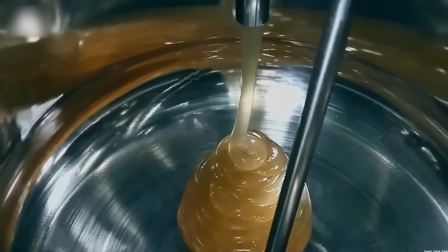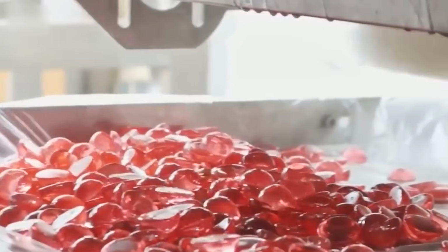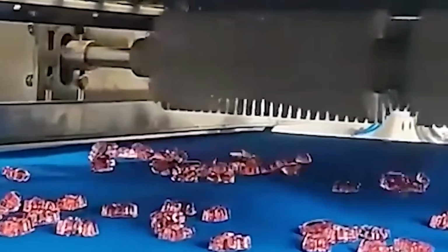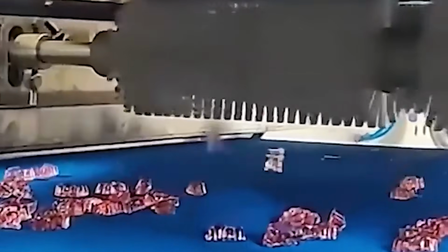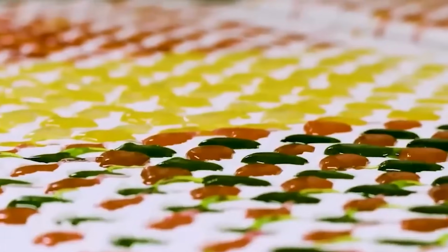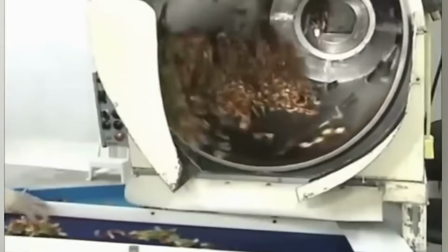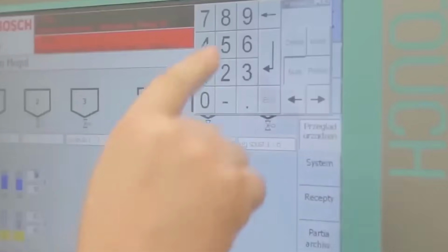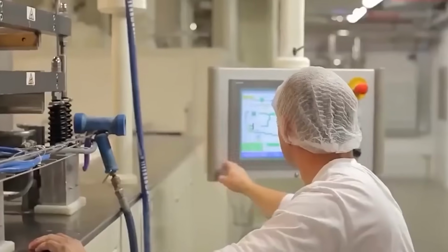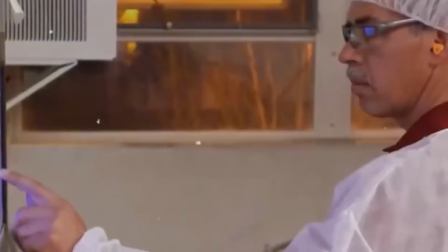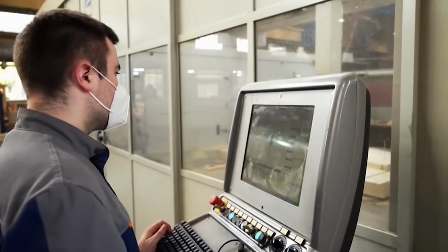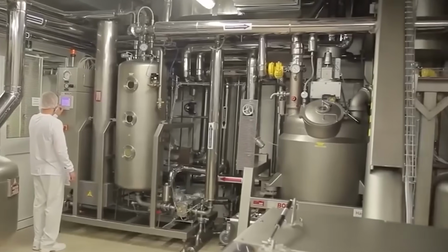Final moisture is the key parameter because it determines how the sheet fractures. Too much moisture produces a tough candy that bends and breaks into large chunks. Too little moisture produces an overly brittle candy that shatters into dust. Temperature and residence time are therefore controlled tightly. Inline density measurement and temperature measurement are used as proxies for solids. Flow control keeps residence time stable, so every portion of syrup receives the same heat history.